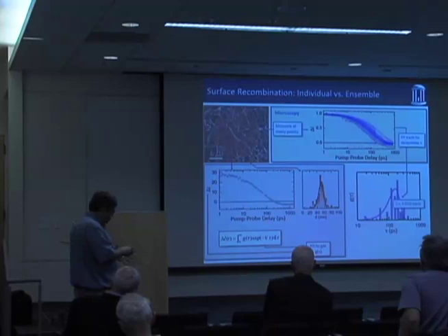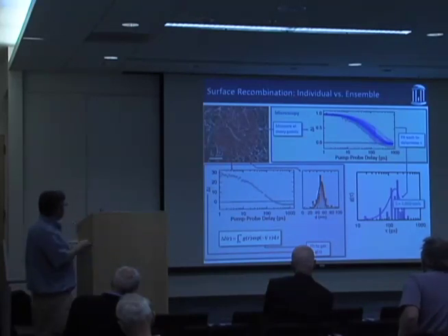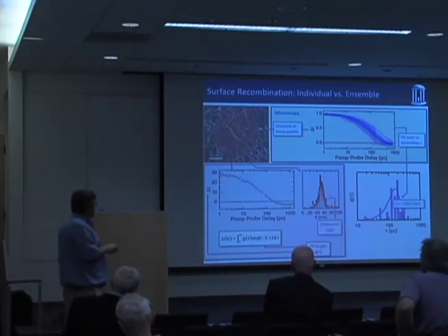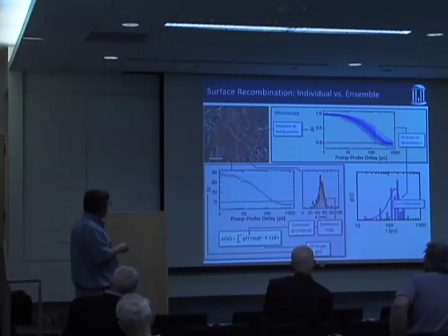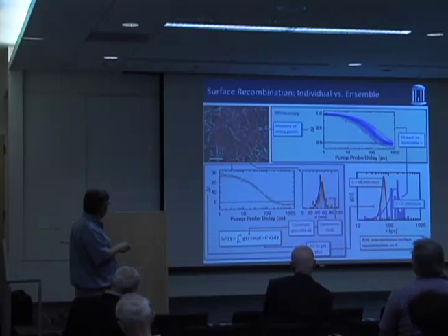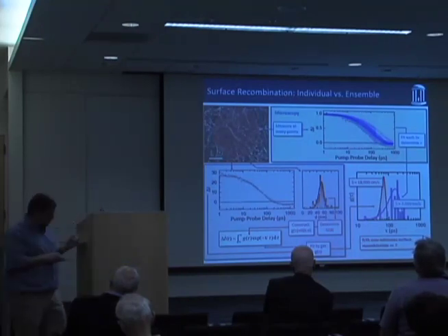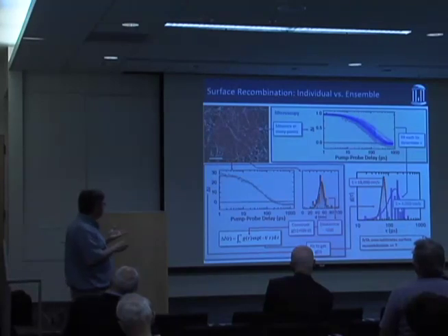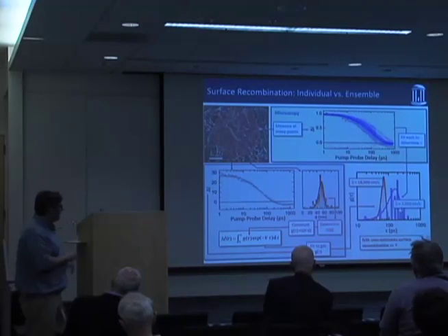And so we took the chip and we went to the SEM and got the distribution of diameters. And we could use that and that little formula that relates lifetime to diameter to get a distribution of lifetimes. And then I could use that in this expression, and when I do that and fit it, I get that distribution. So transient absorption gives me a distribution of lifetimes, and we did this on 4 different samples at different diameters and so on, and it's consistently always faster than what we get out of the microscopy.